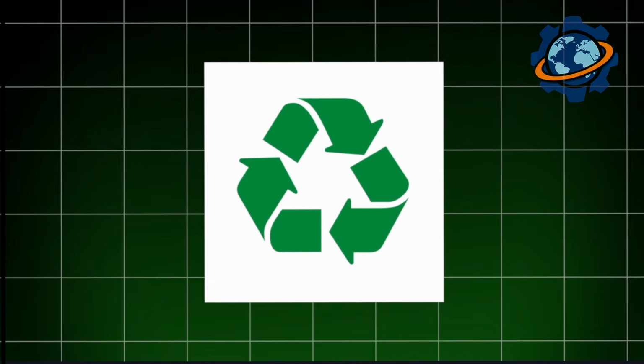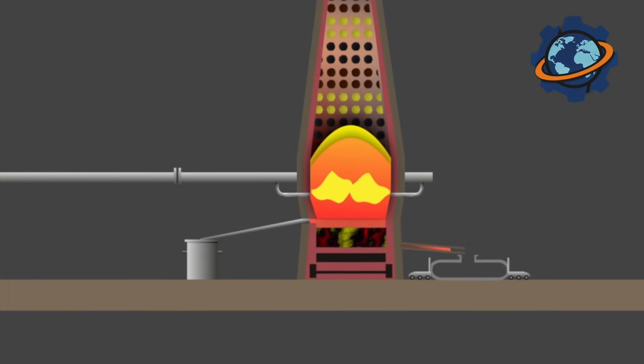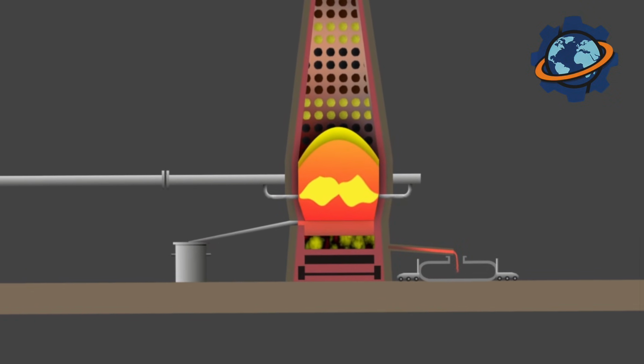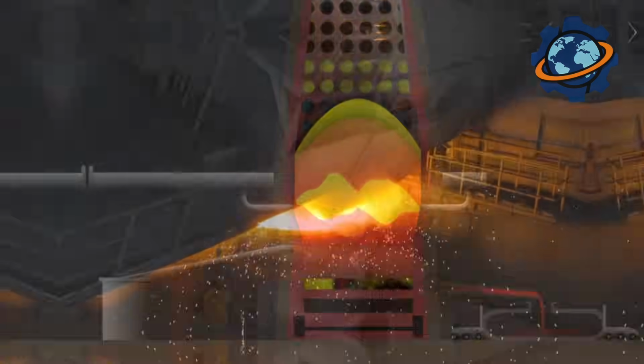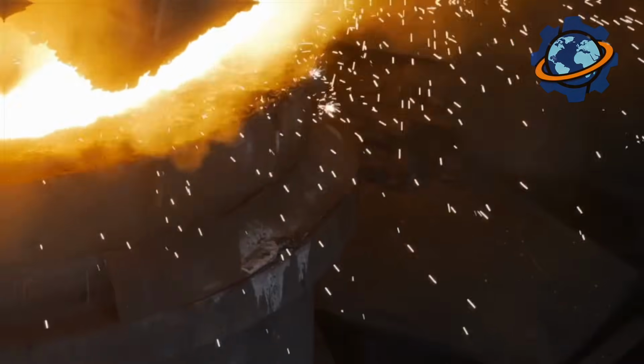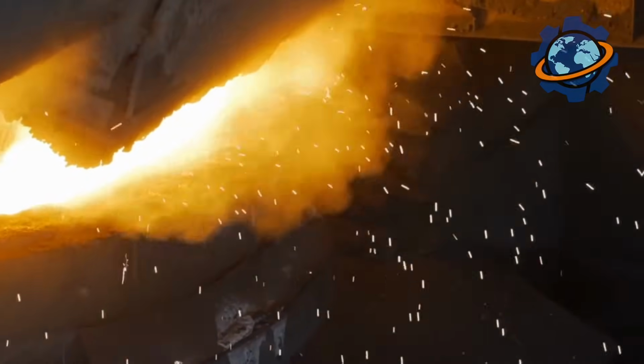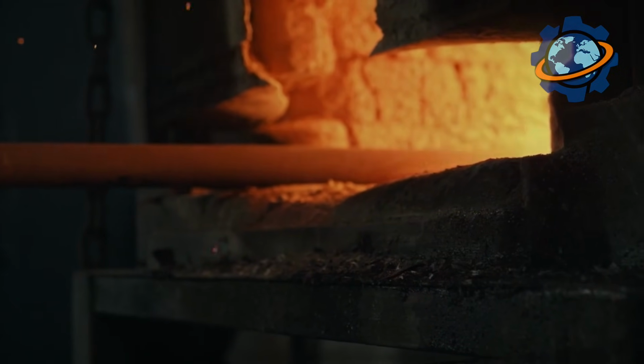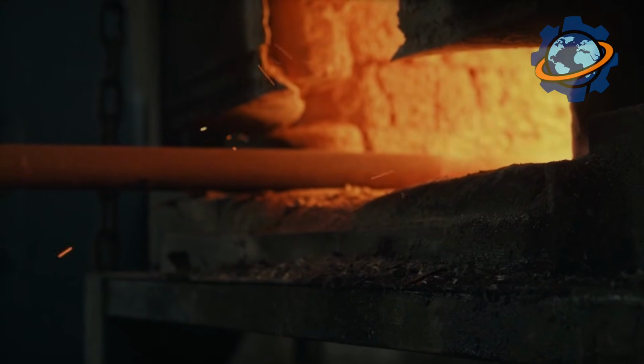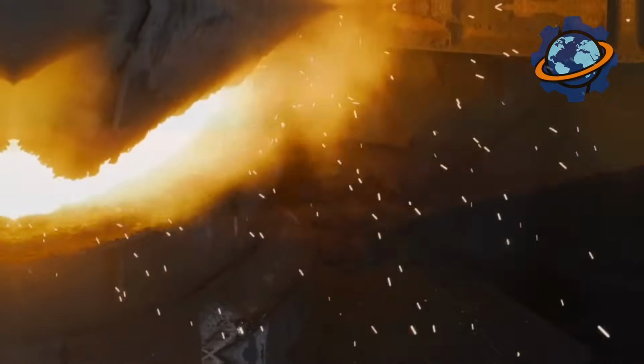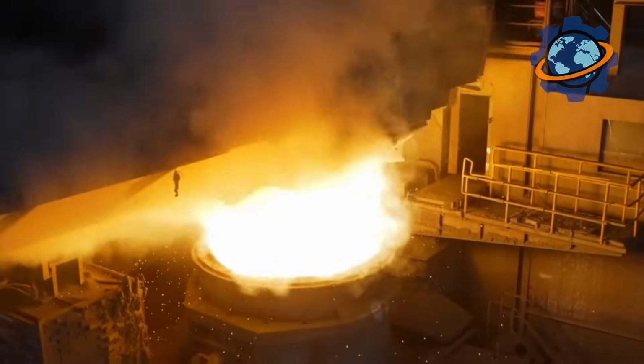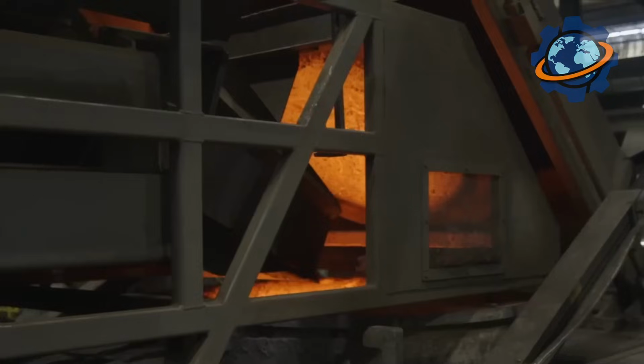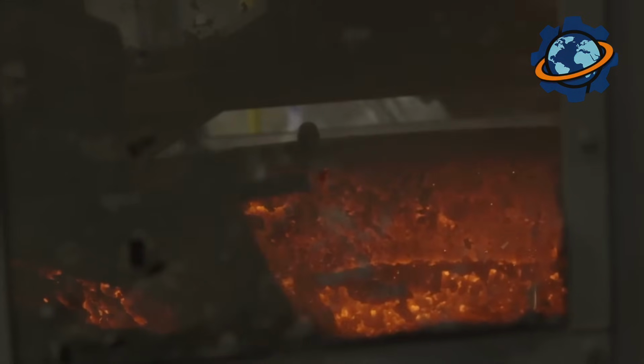The molten iron, called pig iron, contains 4% carbon, too brittle for construction. Picture glass that looks metallic. Drop pig iron from waist height, it shatters into fragments. Next comes the basic oxygen furnace, where pure oxygen blasted at supersonic speeds through 3-foot diameter lances burns away excess carbon in 17 minutes. Flames shooting 70 feet high, temperatures hitting 3,200 degrees, create hurricane-force winds inside steel vessels holding 350 tons of liquid metal.